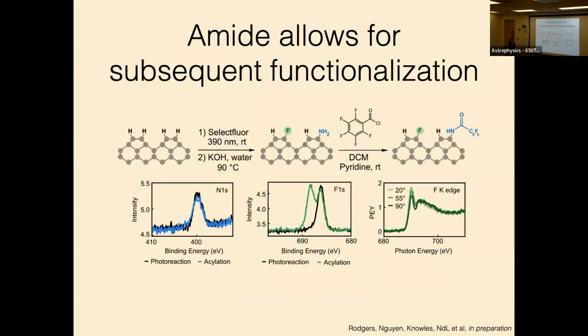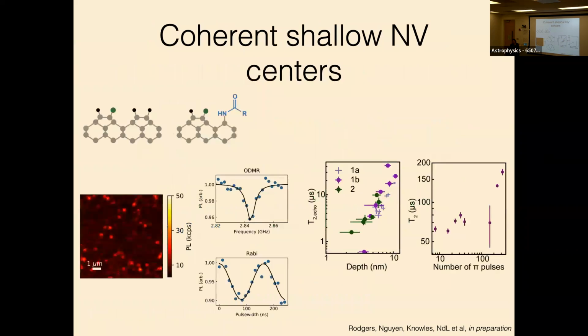Okay, and then this amide group, you can now do all the things that you learned about in freshman organic chemistry to try to attach things to that amide group. We can do hydrolysis to make an amine and then attach that to other things. And then we see that we have them covalently bound to the surface. Importantly, this chemistry is all compatible with making coherent shallow NV centers. So with NV centers that are within a few nanometers of the surface, we can see ODMR, we can drive them. And then if we make a plot of T2 versus depth, all of these different surface functionalizations give us a curve that is basically in line with our typical best. And then we can dynamically decouple, again, up to a couple hundred microseconds.